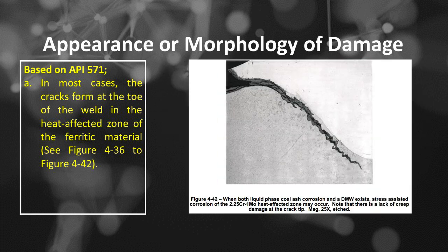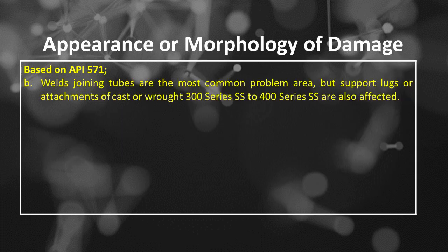See Figure 4:42, when both liquid phase coal ash corrosion and a DMW exist, stress-assisted corrosion of the 2.25 Cr 1 Mo heat-affected zone may occur. Note that there is a lack of creep damage at the crack tip. Mag. 25X, etched. The second of appearance or morphology of dissimilar metal weld damage based on API 571 is welds joining tubes are the most common problem area, but support lugs or attachments of cast or wrought 300 series SS to 400 series SS are also affected.